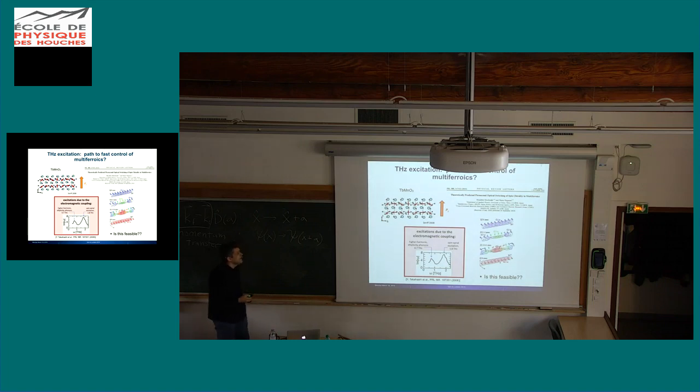So the idea here is terbium manganite is a multiferroic crystal. What that means is that at very low temperatures, it has a phase where you have an ordered magnetic structure, with the uncompensated spins sitting on the manganese sites ordering in sort of a spiral pattern. That's an antiferromagnetic order, and that antiferromagnetic spin order induces a very small lattice displacement, primarily of the oxygen atoms, that induces a small ferroelectric polarization. So this is a case of an induced multiferroic where the actual magnetic order is what is causing this interaction.